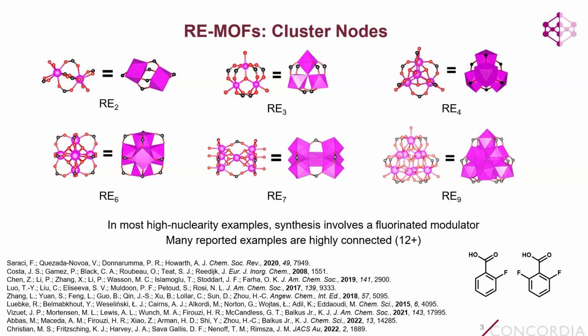And so if we look into the literature at MOFs that have been made with these high nuclearity clusters, we see that the synthesis always involves the use of a fluorinated modulator, something like 2-fluorobenzoic acid or 2,6-difluorobenzoic acid. Originally in the literature, it was thought that we needed those fluoro groups to give some hydrophobicity to the system, to protect these clusters while they're forming and to protect them from hydrolysis specifically in situ. But more recently, researchers have shown that the bridging ligands in these clusters, which are traditionally assigned as bridging hydroxo ligands, mostly through crystallography, are actually bridging fluoro ligands, or at least a mixture of bridging hydroxo and fluoro ligands. So it turns out the requirement for these fluorinated modulators is because we need those fluoro groups to actually make these building blocks.